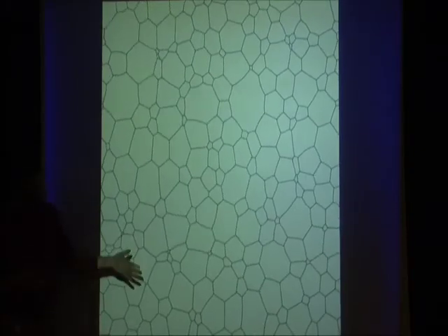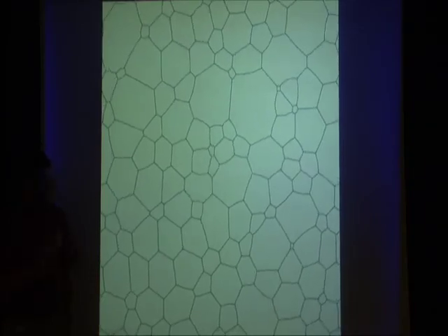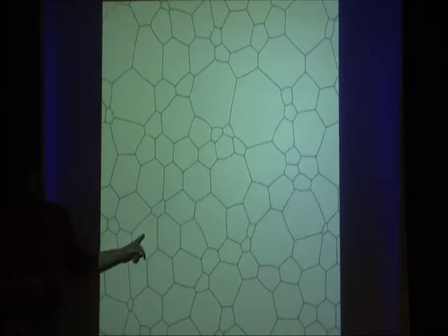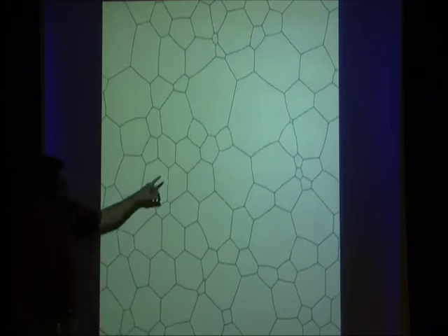Yes. So in the case of this kind of foam, there's actually two time scales. There's one time scale associated with diffusion of gas between the bubbles, which follows the von Neumann relation. And there's another one associated with the redistribution of gas within a bubble, which we approximate as instantaneous, which is why whenever you have a topological event, there's this kind of discontinuous change in the geometry. But this is in fact necessary in order to satisfy this constraint that all the boundaries be arcs of circles. And this is in fact what these systems look like. But when you would violate, you make a jump.